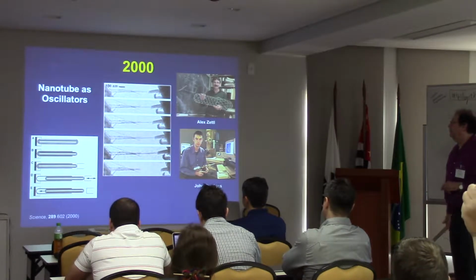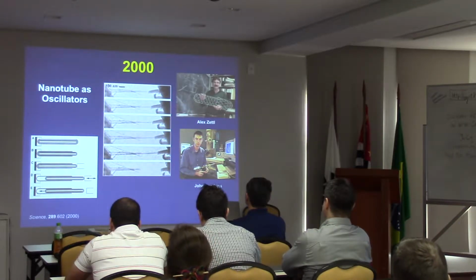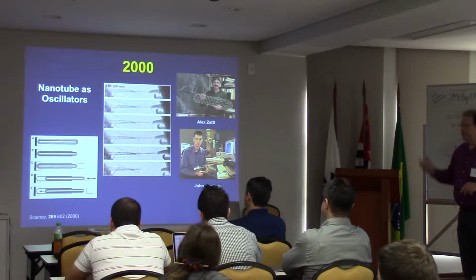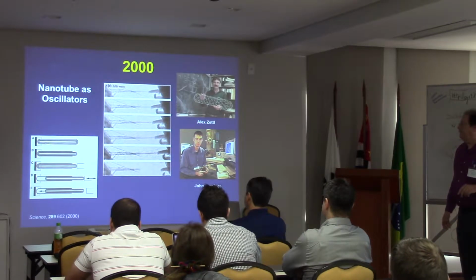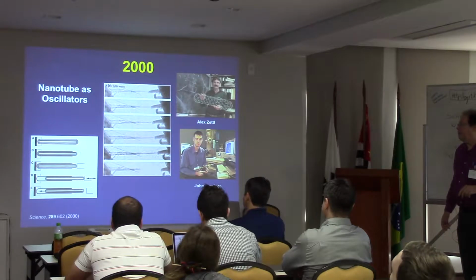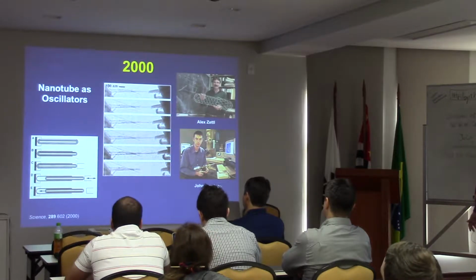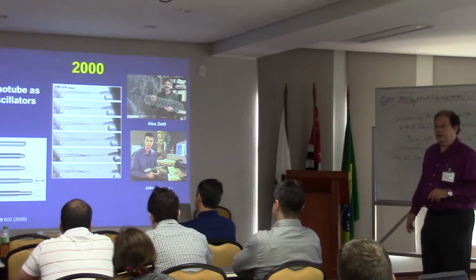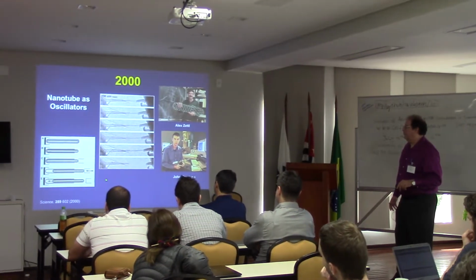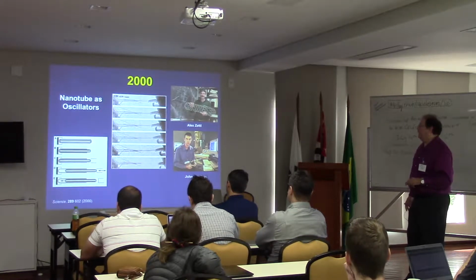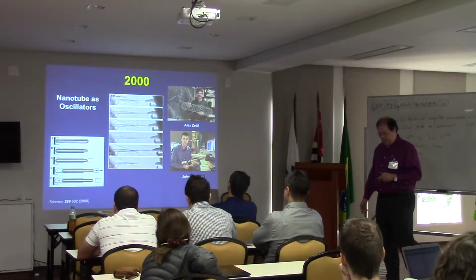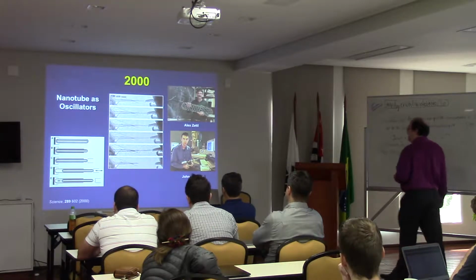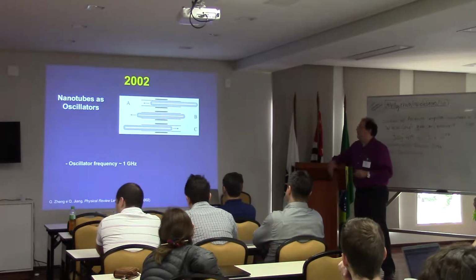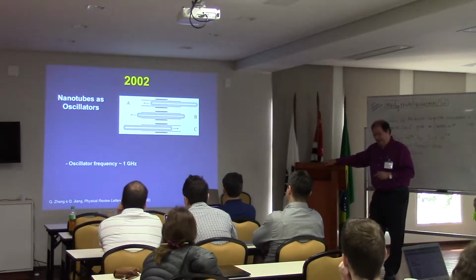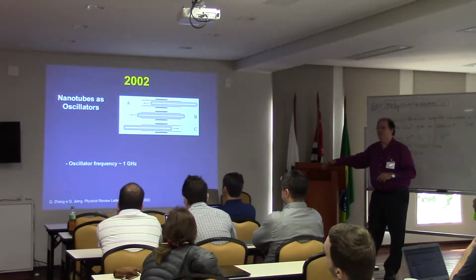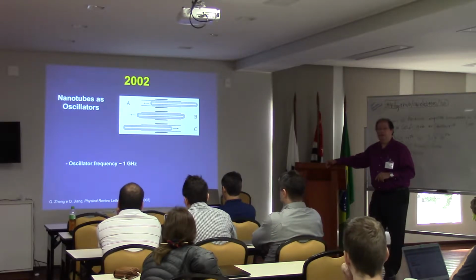So in 2000, there was a very nice work done at Berkeley by the Alex Zettl group. They used multi-walled carbon nanotubes. They immobilized one side, used a chemical etching to open some of the outer tubes while still keeping the inner ones closed, and used the tip to move the tubes back and forth. They showed this could work as an oscillator. More important, this could be a high frequency nano-oscillator. The Chinese, a couple of years later, produced an analytical model that confirmed that this could be a high frequency oscillator.